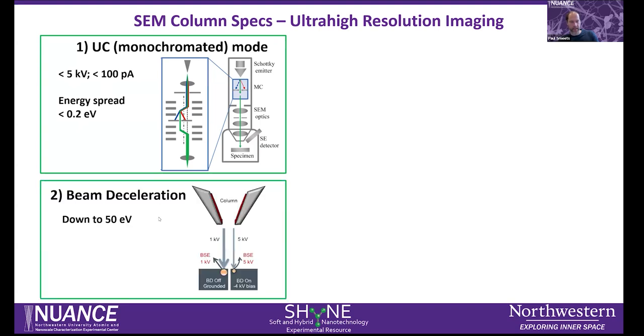The second requirement is that you apply a technique called beam deceleration. Rather than just imaging the direct electron beam directly on the sample, you apply a bias on the stage, and you get a different landing voltage. So you apply, for example, a 5 kV beam, you apply a 4 kV bias on the stage, you get a landing voltage of 1 kV, which gives you higher surface sensitivity and higher resolution signal.